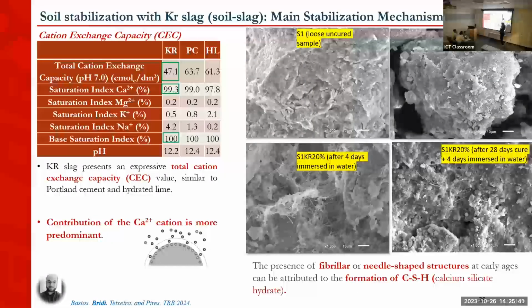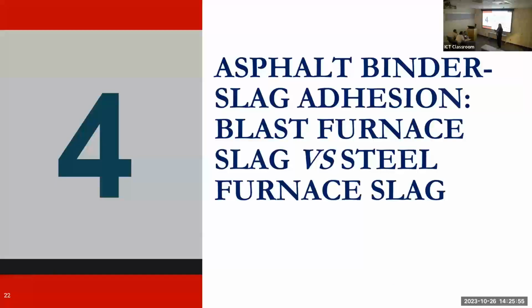So for us, this was evidence that slag was helping the clay soil by cation exchanging, reducing the plasticity, creating agglomeration and flocculation, and also a strength gain because of the hydration of some of the chemical components.